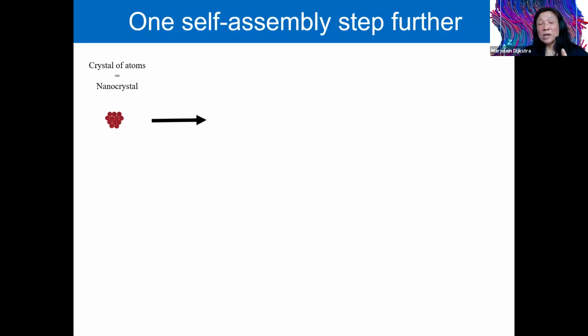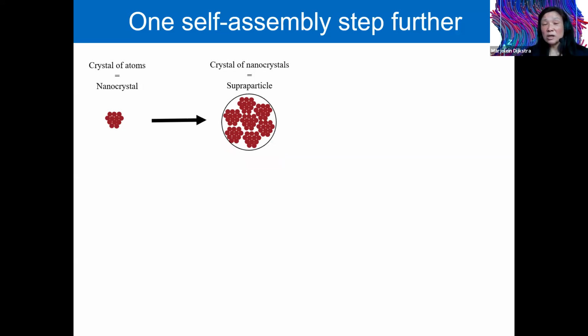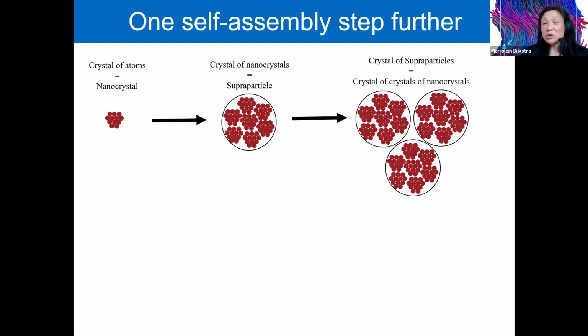What we would like to do here is just to make bigger particles. And so if we start with, for instance, atoms, and we self-assemble them into a crystal, we obtain a so-called nanocrystal particle. If we use these nanocrystals in a self-assembly experiment, we can make all kinds of packings. But if we perform the self-assembly in the spherical confinement of, for instance, an emulsion droplet, we can make a bigger particle out of it. And we call these so-called supraparticles. So these bigger particles can then be used into a next self-assembly experiment to make even bigger structures.